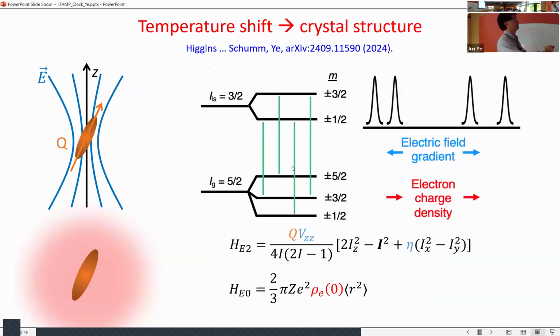You can also use this to study material science. For example, the crystal structure: instead of focusing on the quadrupole moment, you can imagine you put this crystal on a vibrating table and just let the crystal vibrate. That will control the stress, and that would influence the electric quadrupole moment. In this particular measurement, we simply heated up and cooled the crystal by varying the temperature, and you can already see electric field gradient changes and electron charge density changes, and that can move these resolved nuclear quadrupole splitting structures in a way that allows us to fit this Hamiltonian, determining in some sense the material structure using a nuclear transition as a probe.